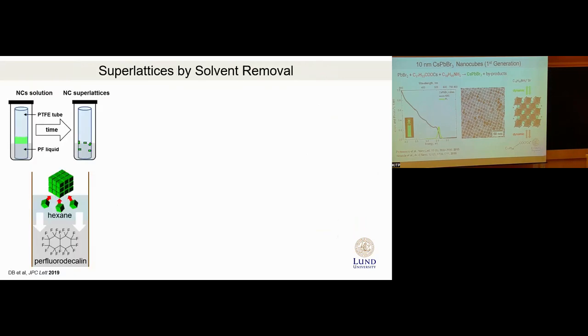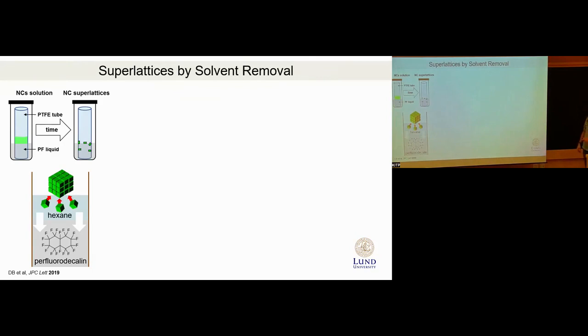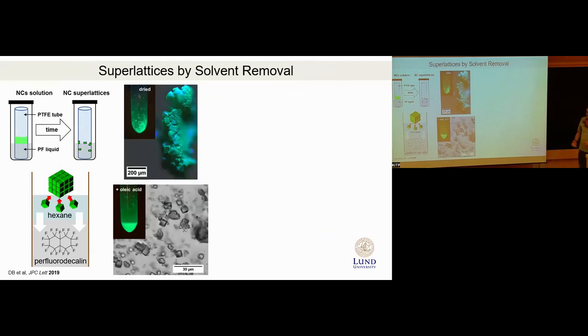So the first superlattices we made were made by solvent removal. So we dispersed nanoparticles in hexane, put them on top of the perfluorinated liquid, perfluorodecalin, which is an anti-solvent for nanocrystals, but is miscible with hexane. So hexane slowly diffuses into this perfluorinated liquid, producing these clusters of cubic particles, which then you can, for example, disperse in oleic acid and further characterize.